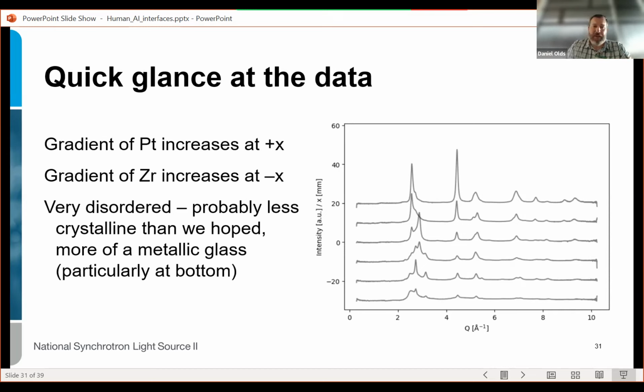We see that the sample is very disordered. We were hoping for something more crystalline, but you know, it's a commissioning study, what do you want? But clearly there's different features to look at here, and our coordinate we could explore was just moving the wafer back and forth. Looking along this wafer in the X direction allowed us to effectively change the composition that we were probing.